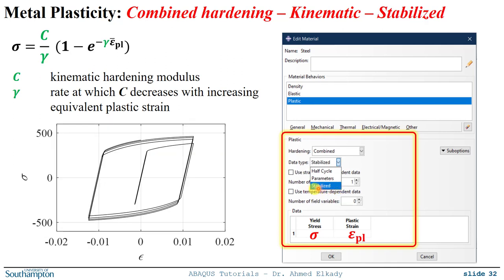The second option is to use the stabilized cycle data, and for this you will need to conduct a symmetric cyclic uniaxial test with a constant amplitude, and you keep doing this constant amplitude in the lab until you get a stabilized hysteretic behavior. Pretty much as you see here, from the start the yield surface, as we mentioned before, starts getting bigger and bigger, but at one point becomes stable or constant. In that case, you can extract this branch of the stabilized cycle outside, and then input the data as stress and plastic strain tabulated data. And again, ABAQUS is going to fit this data with this model to obtain the parameters.